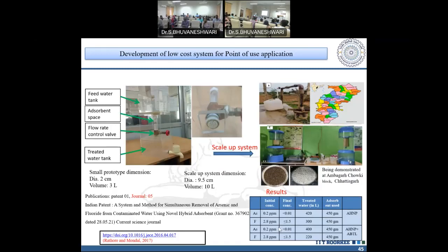And this is our performance. For arsenic and fluoride, these are the initial concentrations, and after removal it is less than 10 ppb. Here the adsorbent used is 450 gram, treating 400 liters. So for 1 kg it will be around 800 liters. In the field we are getting better results than our lab results.